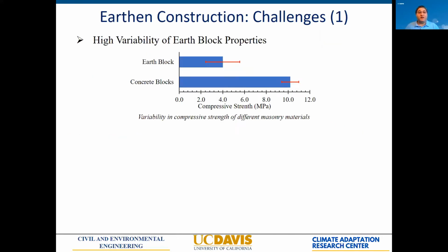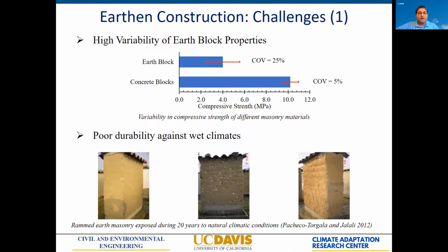There are also some challenges that are connected with this type of construction. The first one is that soil is a natural material, thus it is affected by high variability in the properties. You can see here some results from our tests, where the variability in the compressive strength of earth blocks is about 5 times larger than that of concrete blocks. There is also an issue of poor durability against wet climates. This is an accelerated aging test performed by Pacheco, Torgal, and Jalali, where 20-year aging of this wall was simulated with wetting and drying cycles. You can see at the base of the wall the damage produced by these wetting and drying cycles.